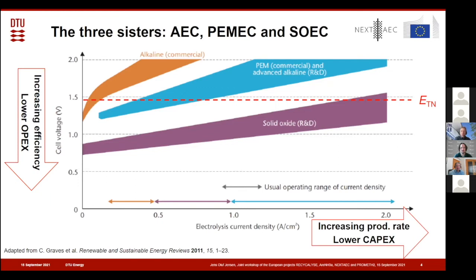So in this graph, we can see that the alkaline comes out the poorest, and the solid oxide is by far the most efficient. The dotted red line is the thermoneutral potential with respect to liquid water, and that is the potential at which the electrolyzer operates completely balanced. So all the energy we put into it is actually stored in the hydrogen that comes out. So there's no waste heat liberated from the electrolyzer.